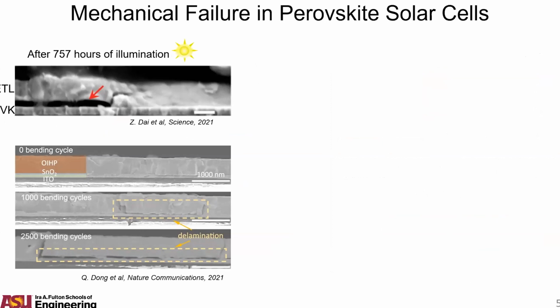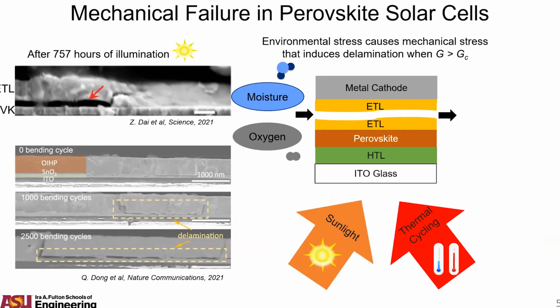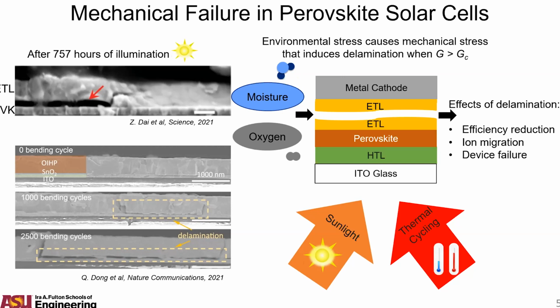So here are two examples of delamination occurring from long-term illumination and also from bending cycles in these structures. Basically, anytime you have environmental stresses such as radiation or sunlight or thermal cycling, that induces these film stresses that can lead to delamination. And of course, then you have effects of efficiency reduction, of increased ion motion, and loss of ohmic contact, and ultimately device failure.